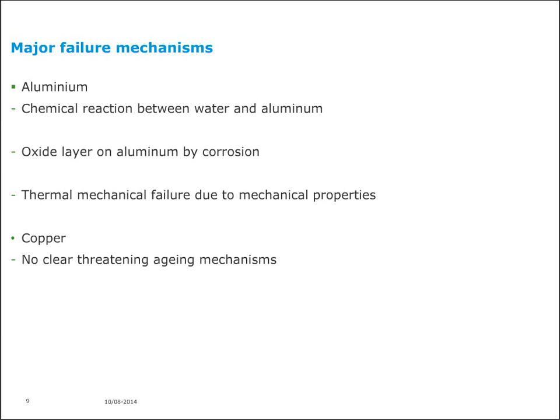Secondly, the oxide layer on aluminum by corrosion. Well-known, aluminum oxidizes very quickly when it's exposed to air, and it gets a thin layer of an insulating material that increases the resistance, and that can result also in problems finally resulting into a failure.